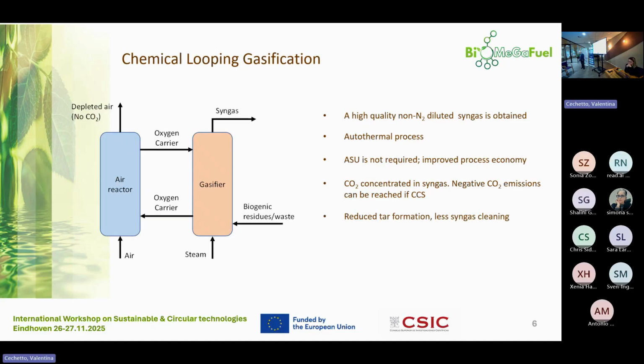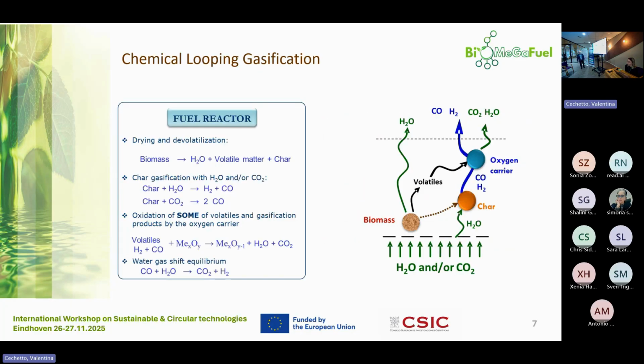Also, the oxygen carrier, the material that we are using, has catalytic properties regarding tar cracking. So we get a reduced tar formation inside the process. And also, as we will see later, it's possible to obtain pure nitrogen at the outlet of the air reactor. It's an advantage from the point of view of the economy of the process. But I want to show you how the process is happening.